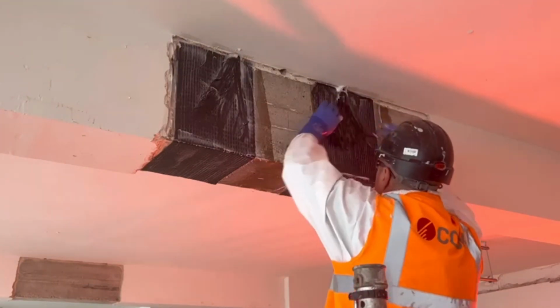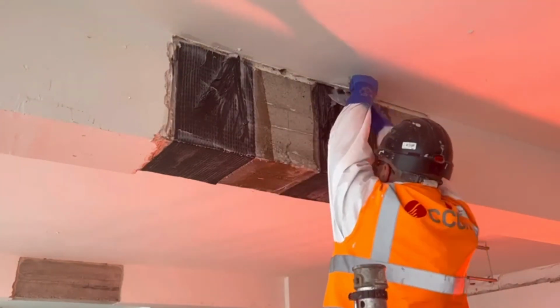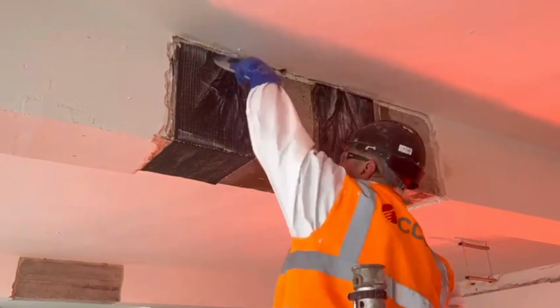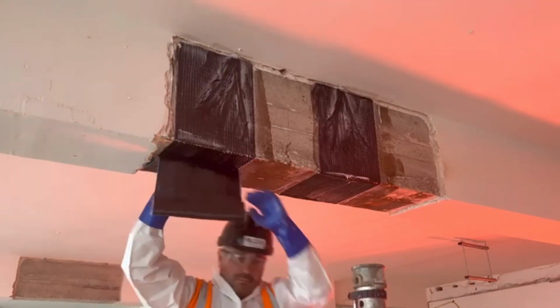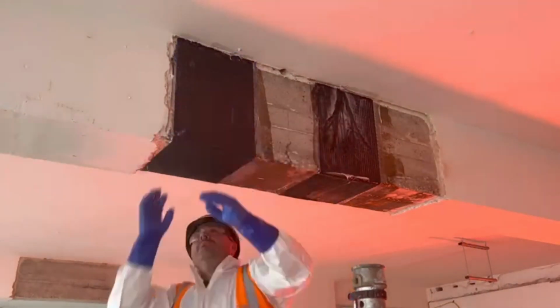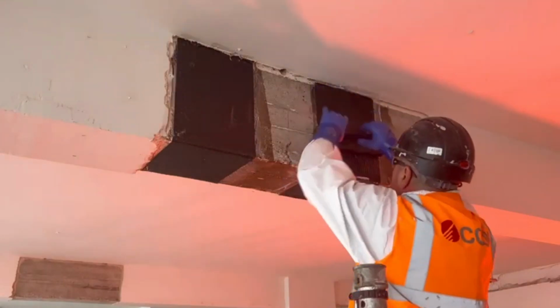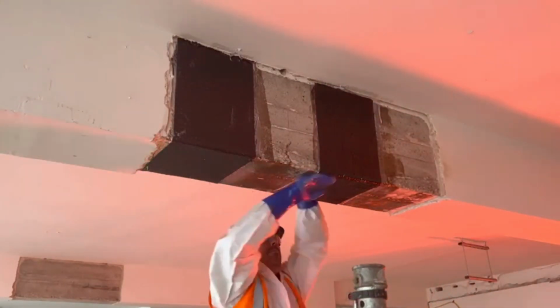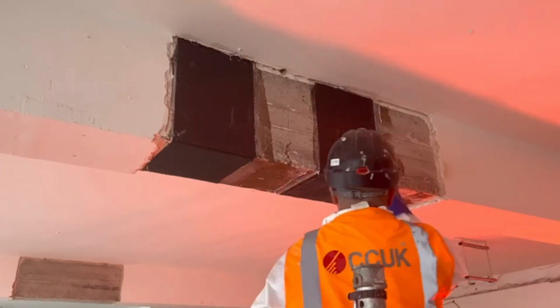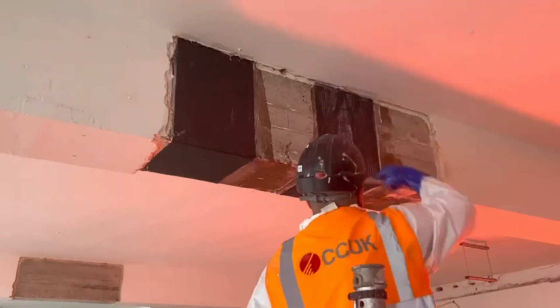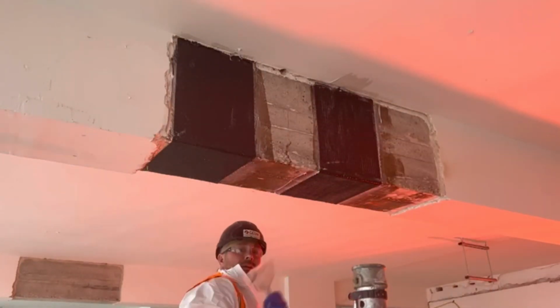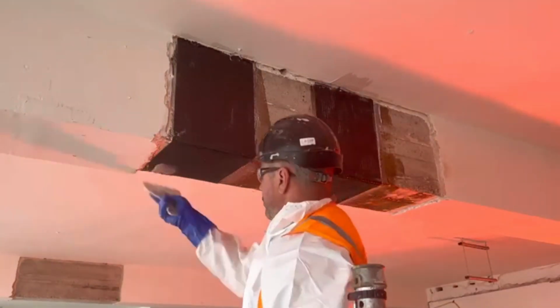So the anchor will be sandwiched between two layers, or if it is a multiple layer application, it will be put in just before the last layer. So it will always be sandwiched between the layers. Yeah. So once that's done, they apply the final coat of epoxy and take out any air bubbles from it. So that's how ultimately the application is done. But again, as I said, it's saturated prior to application, so the application is called the wet layup method.